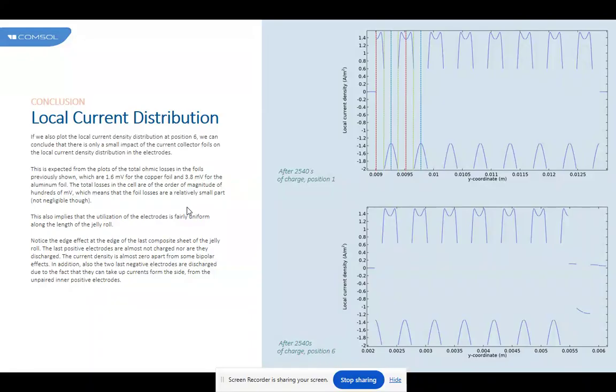This also implies that the utilization of the electrodes is fairly uniform along the length of the jelly roll. Notice the edge effect at the edge of the last composite sheets of the jelly roll. The last positive electrodes are almost not charged, nor are they discharged. The current density is almost zero apart from some bipolar effect. In addition, the two last negative electrodes are also discharged due to the fact that they can take up currents from the side, from the unpaired inner positive electrodes.